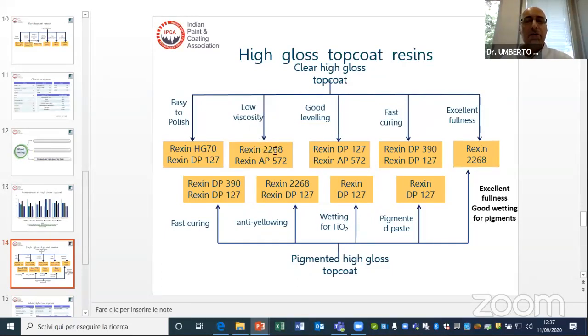It's not very low in viscosity if compared with these two special resins, but it's a resin that allows to make high solid systems too. It is a resin suitable for good leveling system effects. It's a resin suitable for fast curing system. Fullness is not its main characteristic. For fullness, our best resin is Rexin 2268.